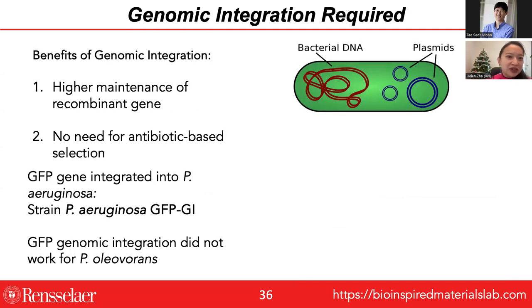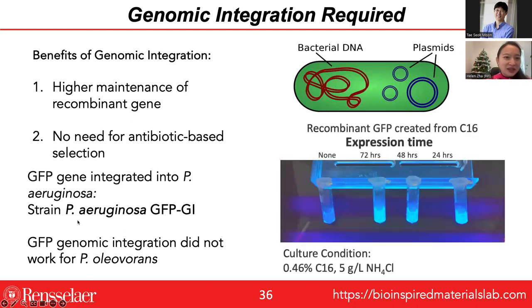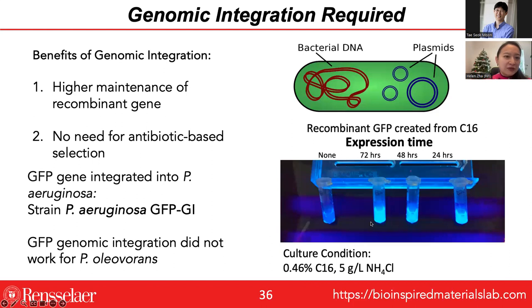By the way, for those who are not familiar, genomic integration means we actually integrate the silk-producing gene into the bacterial chromosomal DNA, and we wouldn't need antibiotic for selection purposes. So we did integrate, first, a green fluorescent protein, just as a test, into the genome of Pseudomonas aeruginosa. We couldn't do that with Pseudomonas oleovorans. It didn't quite work. But what we did find was the ability for this strain to produce green fluorescent protein while using hexadecane as the sole carbon source.